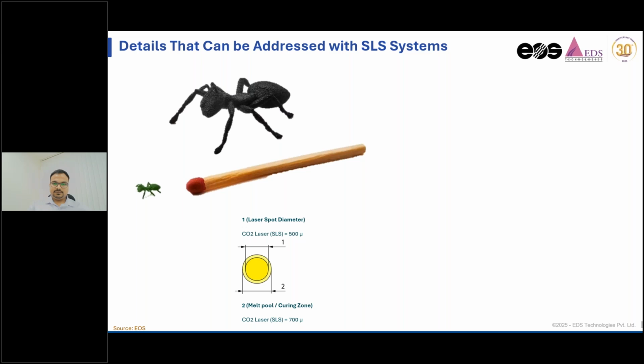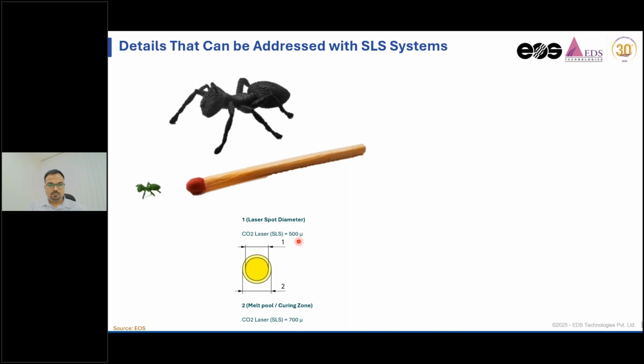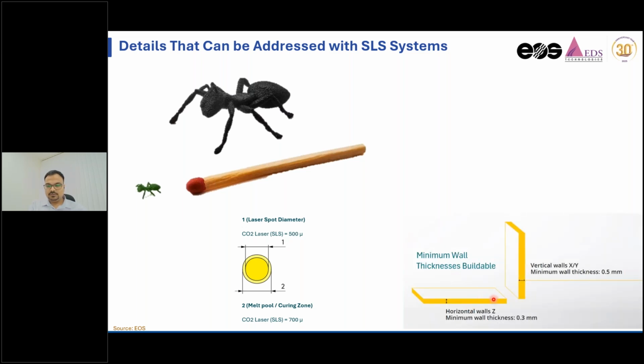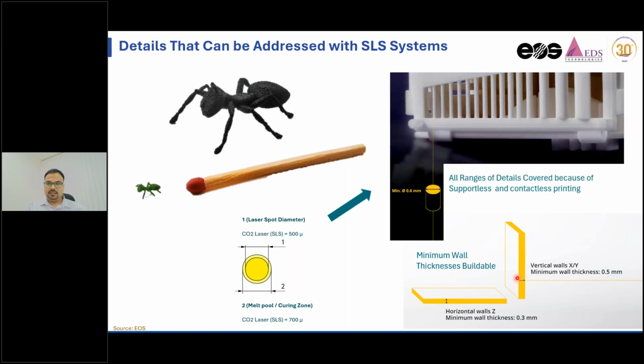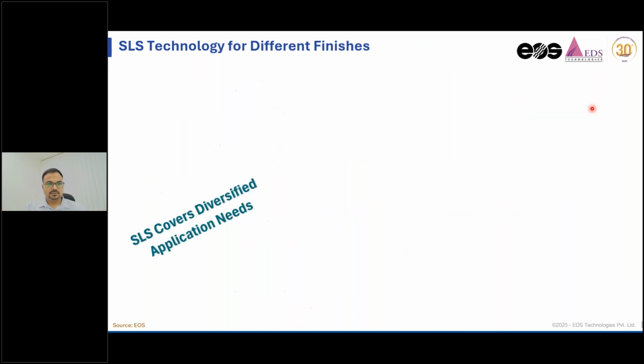What amount of detail can it address? As I mentioned right before, it is able to address starting from 0.5, because the laser diameter is 0.5. So you can see the horizontal walls that can be manufactured. The minimum wall is ideally 0.3 mm, subject to your overall component size, and the vertical features that can be printed are 500 micron ideally. And these are the results you can see, from this size of the feature all the way to the size of the bucket. We are able to print and address today.